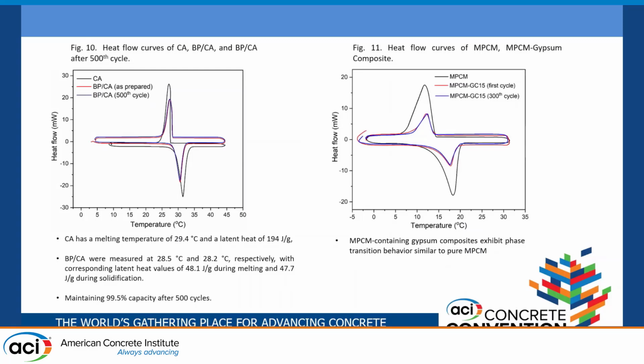You can see the DSC test results. So we are testing the pristine capric acid. We are testing the basalt powder capric acid composite. And what we are doing is we are trying to do 500 times heating and cooling, and we are trying to see if these materials are thermally stable. Can they maintain their phase transition or heat enthalpies? So both the pristine capric acid PCM and the composite that we have produced have very similar heat behavior, and after completing 500 cycles of heating and cooling, we are maintaining 99.5% of the heat storage capacity.